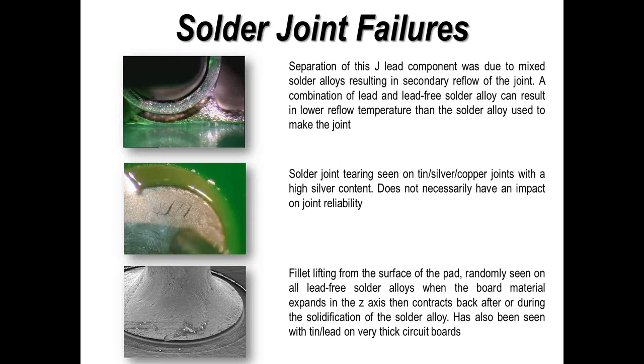Second example is where we're getting cracks or, dare I say, perhaps more appropriately, tears in the surface of the solder. The solder manufacturers don't like the term cracks, but it's really a tear. And what you will have with tin silver copper alloy joints, and you can have this with selective soldering, pin and paste soldering, or wave soldering, is in the surface, as the solder solidifies, you can get these tears in the line. It tends to happen more with the higher silver content tin silver copper materials, and it's covered under IPC. Also, pad lifting and fillet lifting.